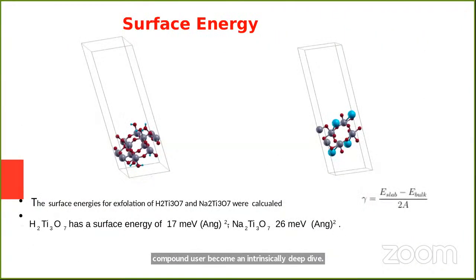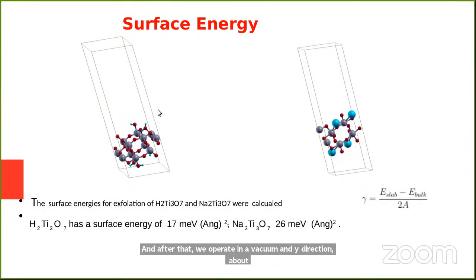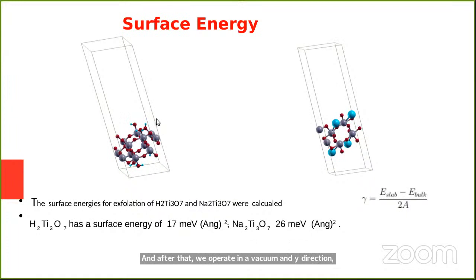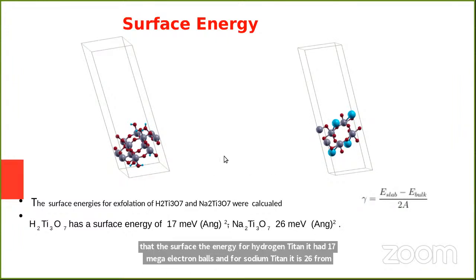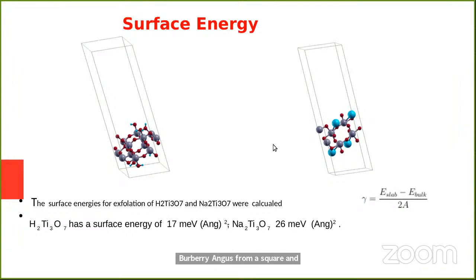And after that, we open a vacuum in the Y direction, about 20 angstrom, and the structure is relaxed. Then we calculate the surface energy by using this formula. We obtain that the surface energy for hydrogen titanate is 17 meV and for sodium titanate is 26 meV per angstrom squared. This means the two compounds have low surface energy, promoting exfoliation of the bulk and the formation of 2D material and nanotubes.